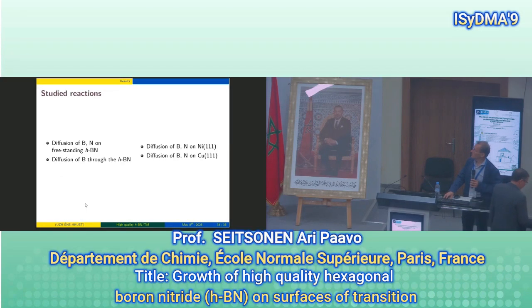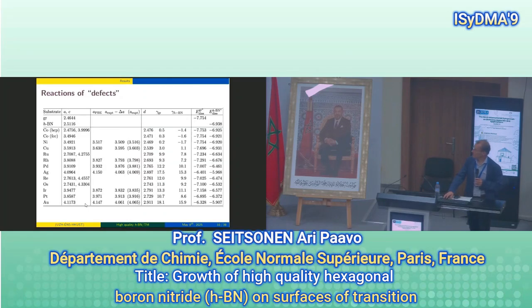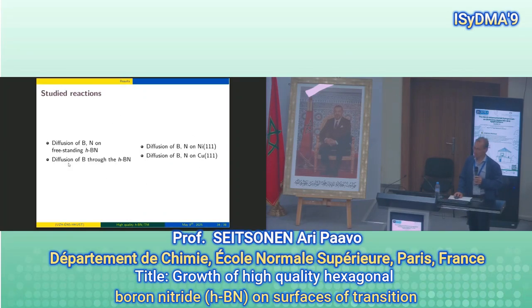And to end, I just mention we have recently started to study the adsorption of defects on the hBN, so adatoms in this case, just at the surface. This is the part that we initially started in freestanding hBN, and now we are doing the same on the substrates. We use two different examples. The boron nitride on nickel 111 is actually commensurate, which means that they have the same lateral lattice constant, or very close to it. Also on copper, the lattice constant is quite similar, but the interaction is weak, whereas it's strong on nickel. So we plan to use these two substrates to study, for example, diffusion and penetration of the boron through the hBN layer.